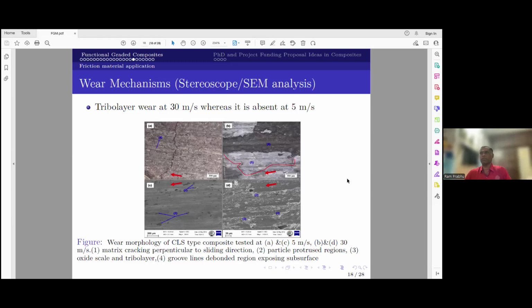Then the postmortem. The postmortem is to understand what kind of wear mechanism is operative at different speeds. So we observed many different things: cracking, vertical cracking, delaminated regions, tribo layers. You can see the tribo layers very well, and particle protrusions, only the particle pop-ups, some groove lines. At low sliding speed we don't see any oxidation or delamination. Mainly we see the cracking and the groove lines, which is nothing but abrasion wear.